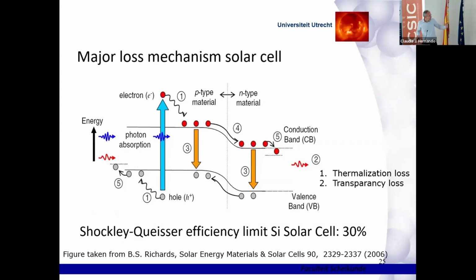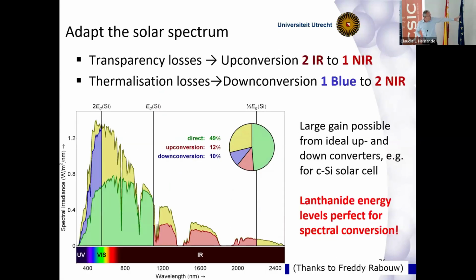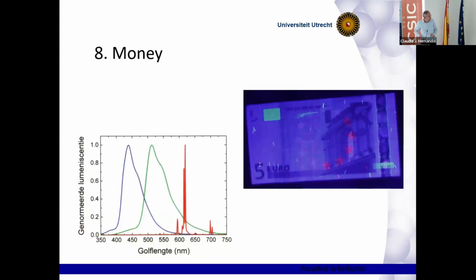And again, lanthanides can be used by using up conversion, down conversion to add up two infrared photons that are not used by the solar cells to convert them to higher energy photons that can be absorbed, or by splitting one photon in the high energies to two photons of lower energy that both can be absorbed, getting current doubling. So lanthanide ions can enhance the efficiency of solar cells by 22%.